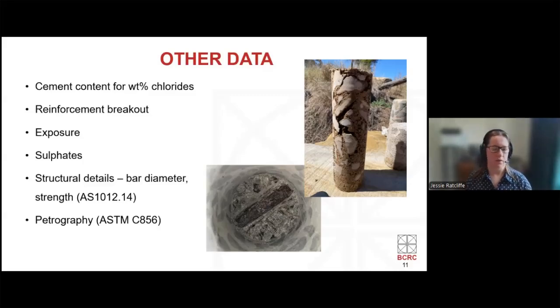We can also look at the reinforcement, do a breakout, particularly in areas that have those defects that we noticed in the first stage, and assess any corrosion on the reinforcement, measure the size, and see if it's a plain bar or deformed bar. Can also consider measuring sulfates if our exposure suggests that might be a problem, and find structural details such as compressive strength of the concrete and the bar diameter.